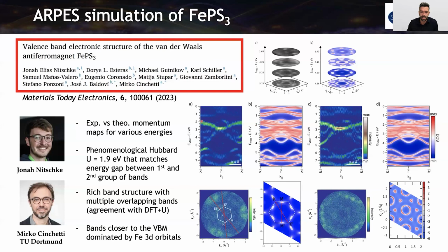So in this case, we fitted this gap here that is around 0.9, if I don't remember badly, electron volts, and we needed a Hubbard U of 1.9. That corresponds to the one that is reported in the literature, that usually is like 2.1, 2.2. So with this, we could match this gap here, and then we have these similar shapes here, for example. So we were also revealing the rich band structures and which are the orbitals. So closer to the valence band is dominated by 3d orbitals.